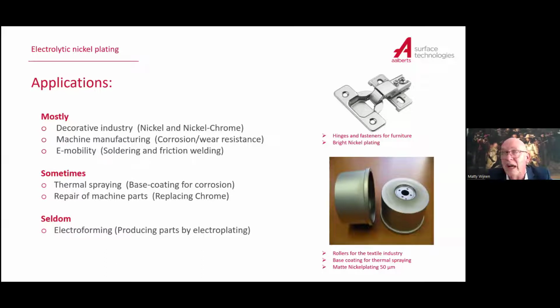If you put a very shiny layer onto metals and you put a thin layer of chrome on it, you have a typical layer system. We say it's chrome plated, but it's not chrome plated, it's nickel chrome plated. A thick nickel layer, which is nice and shiny, and a very thin chrome layer on top, which is not seen at those layer thicknesses, but gives you the corrosion protection of the nickel. So the nickel won't discolor, and it isn't damaged, due to the fact that chrome is very hard.